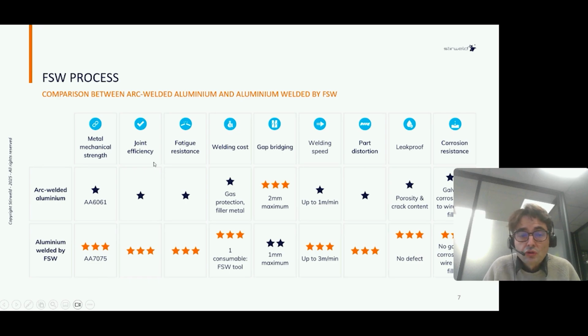The same thing, joint efficiency is where we measure the tensile property. We observe exactly the same for fatigue resistance. Generally the fatigue resistance of friction stir weld is 2 times higher than arc welding. Now, what about welding cost? For arc welding, we use shielding gas and we use filler metal.